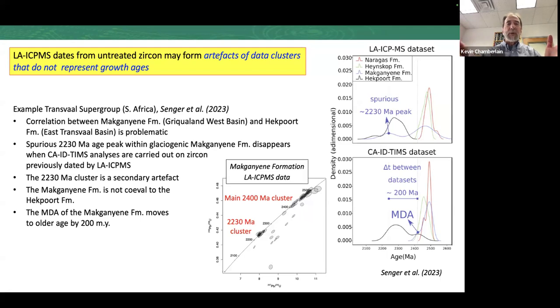And so the problem arises when you have a mismatch between the downhole fractionation of your standard, which you then apply to the downhole fractionation of your unknown, and the rate at which it's digging can be either faster or slower. You often get dates that are too old from laser ablation, as well as too young. And that's because of this matrix effect. If you anneal the zircons first, you've minimized that, and the variation in your laser dates becomes much tighter, much smaller. You still have lead loss, you still have a lot of the other factors, but that step alone improves the laser data immensely. And it only takes a furnace and 48 hours and some crucibles. It really should be adopted across the board. Every laser lab should be doing this.